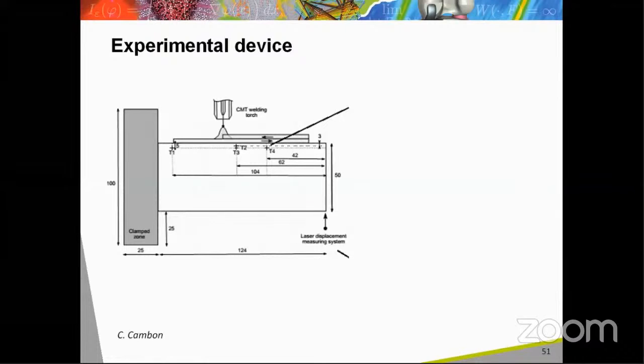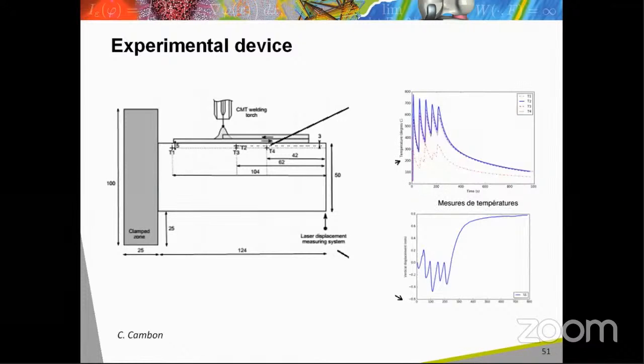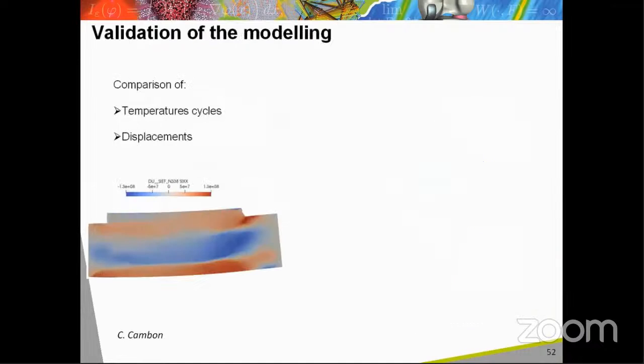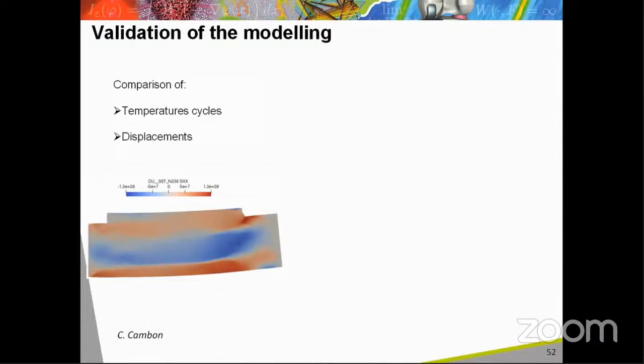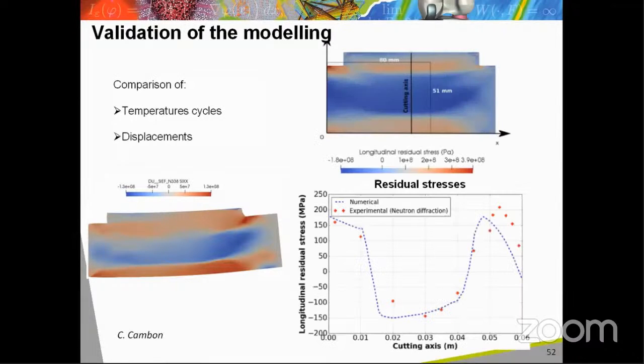The experimental device is instrumented to measure during the WAAM deposit the temperature evolution with thermocouples and the displacement of the plate using a laser displacement measuring system. In addition, residual stress measurements have been done by neutron diffraction. The validation of the modeling has been done by confronting the temperature cycles and the displacement evolutions predicted by the model with experimental measurements. And finally, the predicted residual stresses have been compared with the results of neutron diffraction measurements.